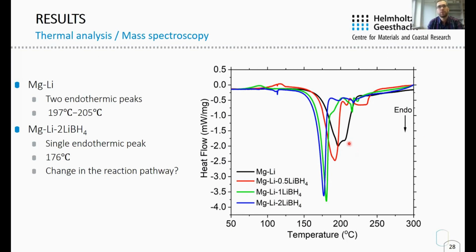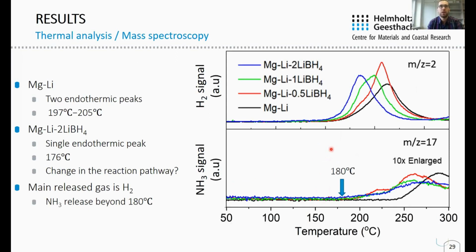There are two endothermic peaks around 200 degrees, and this peak temperature is lowered by addition of lithium borohydride. For example, by adding 2 moles, the dehydrogenation peak temperature is located at 176 degrees, and it has a single dehydrogenation peak. The present single dehydrogenation peak instead of 2 is most likely due to a change in the reaction pathway. Additionally, the ammonia release is also shifted to 180 degrees, and the main released gas is hydrogen from this sample.